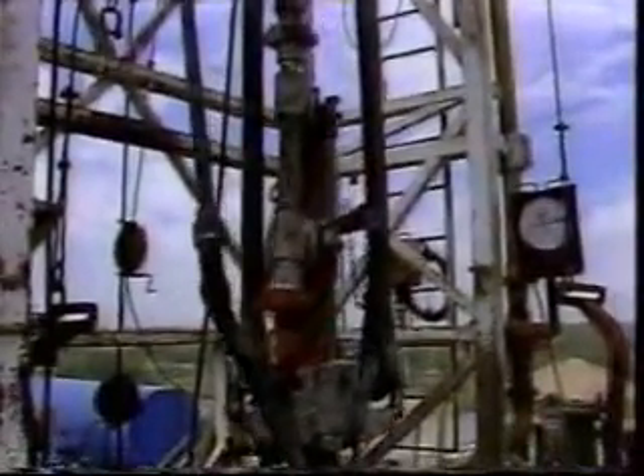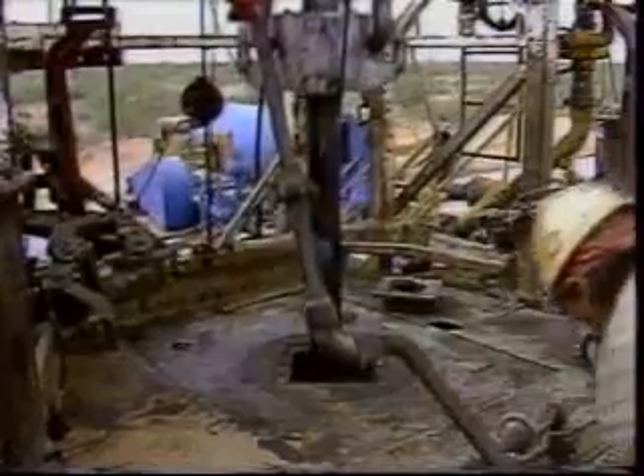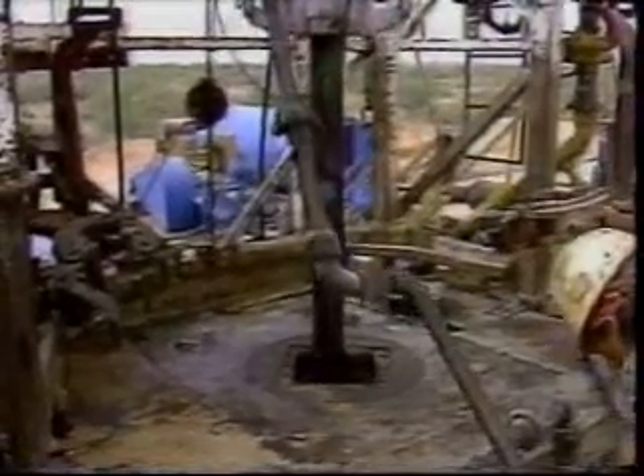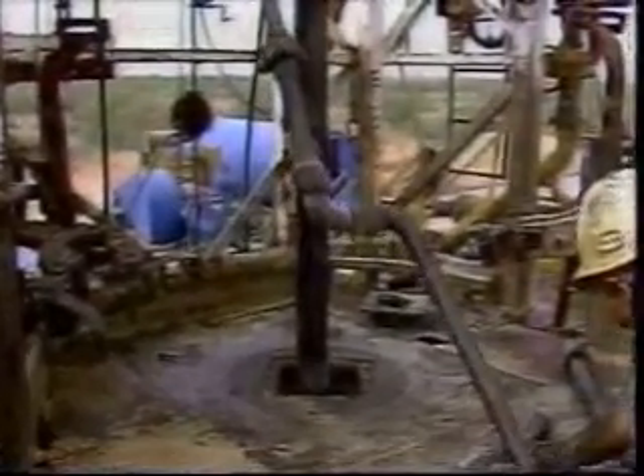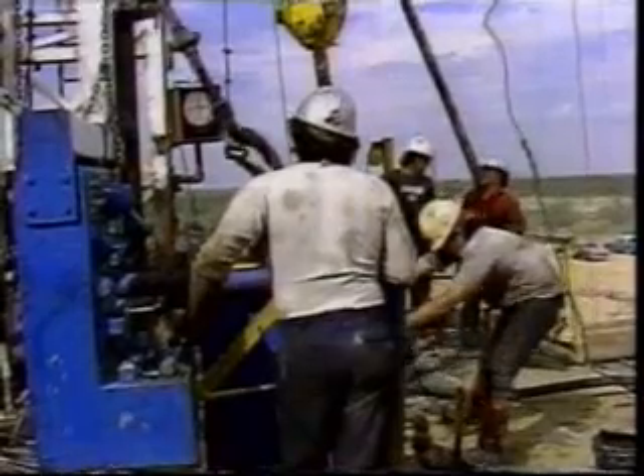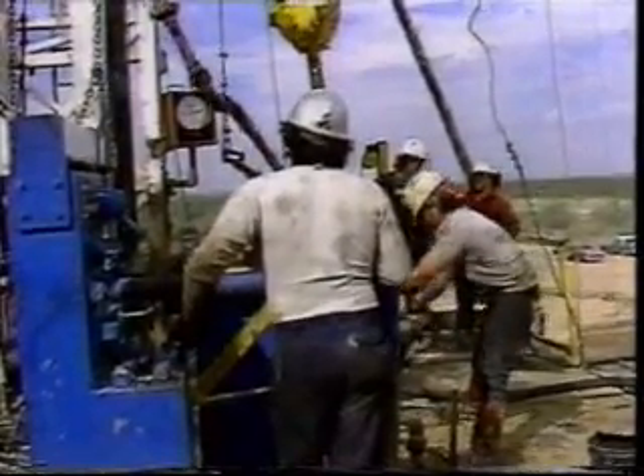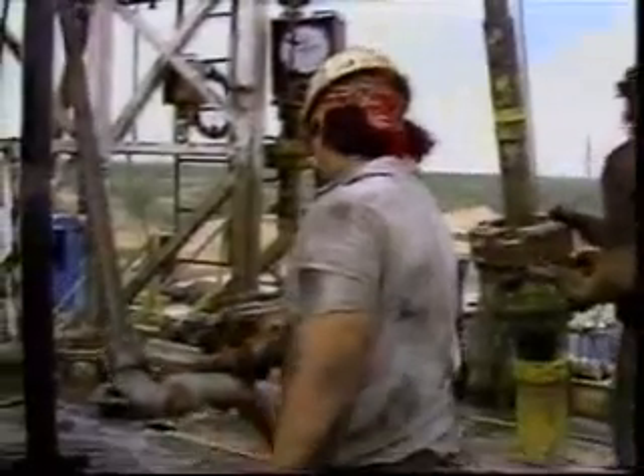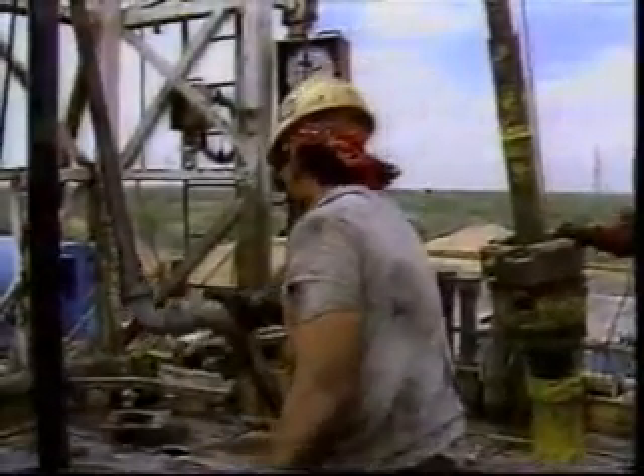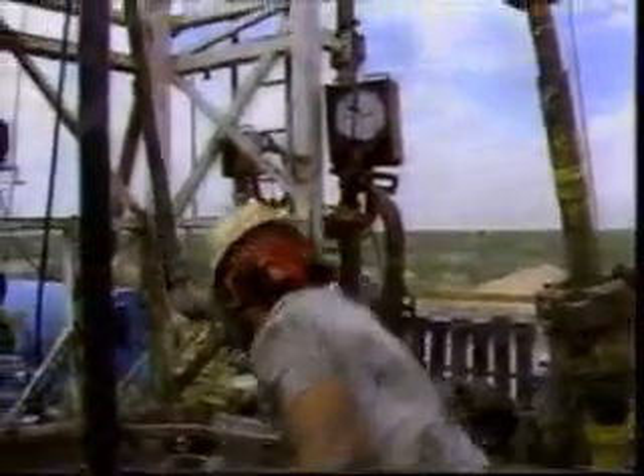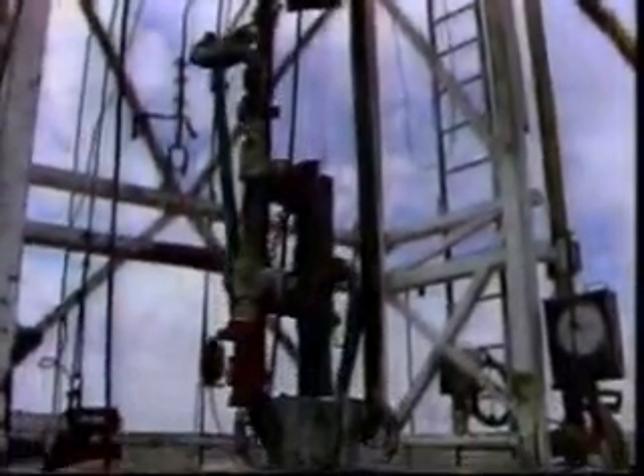And the reason for this is if you look at the wellbore in a cross section, because your casing is always going to be slightly off center, there's a wide side of the hole and there's a narrow side of the hole. It requires quite a bit more energy to move the mud out of the narrow side of the hole than it does from the wide side. So the purpose of the pipe movement is to always change that wellbore geometry so that what was the wide side at the top of the stroke might be the narrow side at the bottom of the stroke.